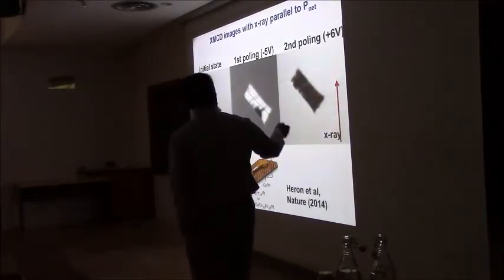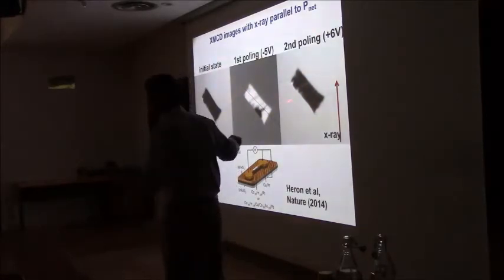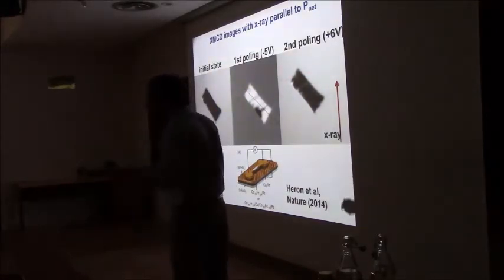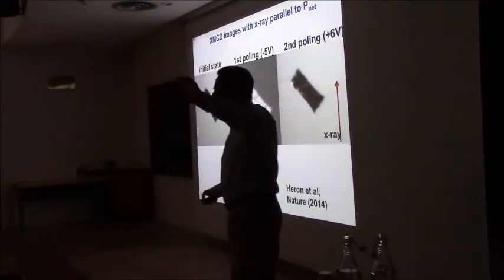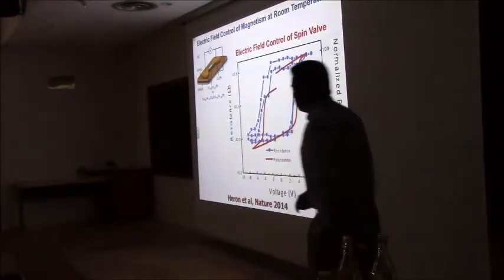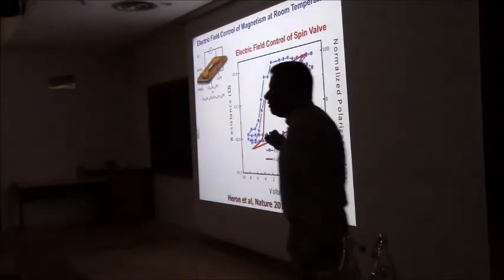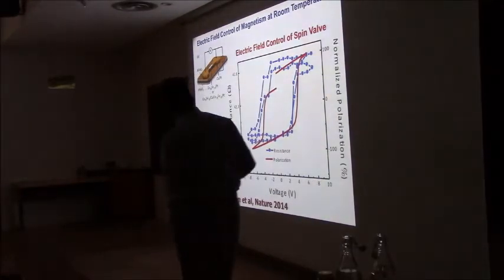Yeah, that's the device structure that we were using. You can rotate the sample or the X-rays for that matter, and you can image the stripes. Indeed, you can see that the magnetism is switching by 180. That's all outlined in this way. Okay, very good. You can go back and do other measurements. I'm going to focus for the next 5 minutes or so on other measurements.